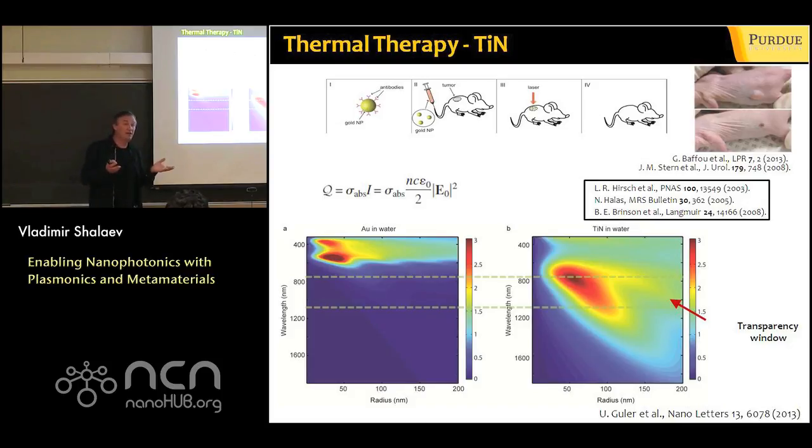But when you make these nanoshells in a chemical way, they become relatively large, 110 nanometers, and when your colloidal particle is large, it could be a problem because they could stay in your liver and kidney. It's harder to remove them from the body. Also, you use all these surfactants to make these particles chemically, which makes the particle even stickier. With titanium nitride, in contrast, if you do nothing, if you just take a colloidal particle of titanium nitride, with no structure, it absorbs exactly in the biological transparency window. You don't want to shape them in any way.